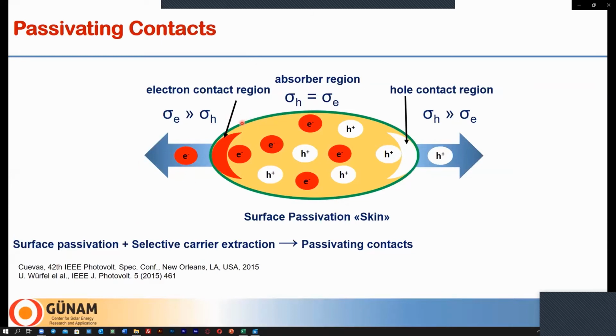You can form this skin by applying some passivation like silicon dioxide, intrinsic amorphous silicon, aluminum oxide, make some doping, or apply some material with different work function. However, you need to extract these electrons and holes in a solar cell, and you need metal contact for that. And when this metal contact structure, with different dielectrics, can passivate the silicon surface and selectively extract one type of the carrier, we are forming what's called the passivating contact.